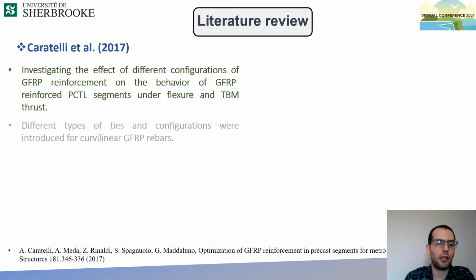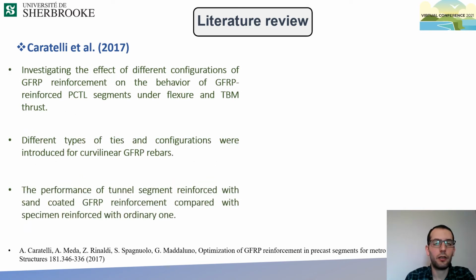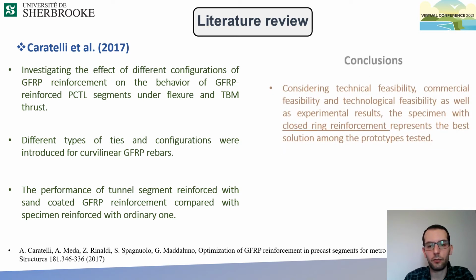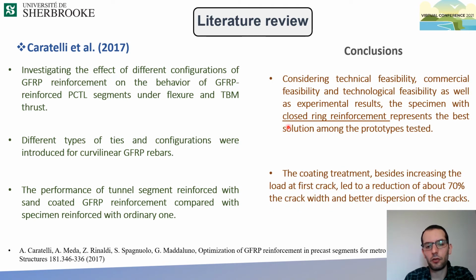In 2017, Caratelli et al. investigated the effect of different configurations of GFRP reinforcement on the behavior of GFRP reinforced PCTL segments. Different types of ties and configurations were introduced, and the performance of sand-coated GFRP bars was also compared with the specimen with smooth bars. They concluded that a closed ring reinforcement, which is closed in all directions, is the best prototype tested, and also the coating treatment improved the cracking behavior by 70%.